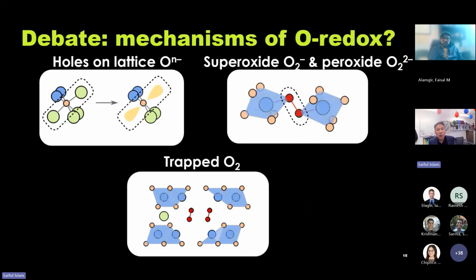So what is the debate? Well, the oxygen redox species could be, on the top left, localized holes or delocalized holes. On the top right, there is evidence that there is dimerization. So could it be superoxide or peroxide? Or on the bottom, could it be trapped molecular O2 in the bulk? And all of these have been proposed, and I'm going to show you evidence for particular oxygen redox species.